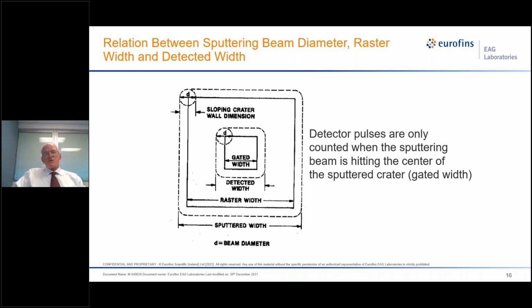You can't shrink the beam, the crater, the gated, the analyzed area as small as you might want, because we can only use every atom in this area once, unlike Auger or XPS, which can continue to irradiate the sample and get signal repeatedly from those atoms because they remain in the sample. In SIMS, we sputter those atoms off, so we can only use them once. So if you shrink this gated area too small, there won't be enough atoms left to give a usable signal, because remember from the previous slide, most of the sputtered particles come off as neutral atoms. We play some tricks to make as many ions as we can, but you can't make the analyzed area basically infinitely small. You run out of atoms.